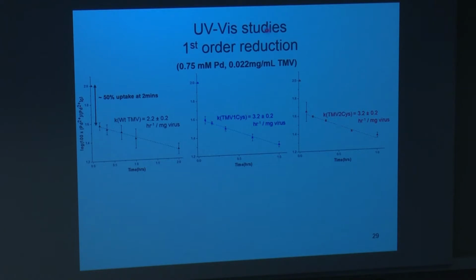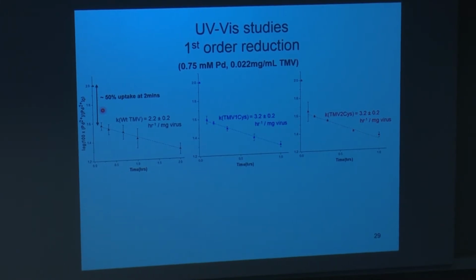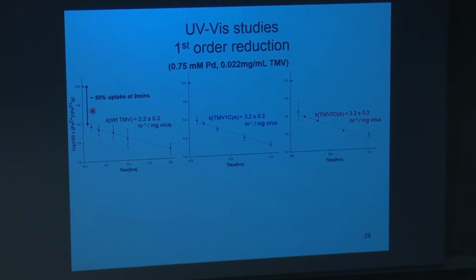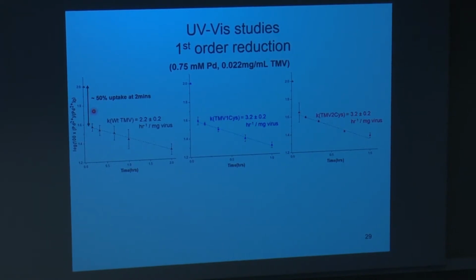And using the UV-Vis spectrophotometer, we had an initial solution of 0.75 millimolar palladium and 0.022 milligrams per milliliter of TMV. The initial solution was here at level 2, and this axis here is log of 100 times the palladium ion concentration at time t divided by the initial palladium concentration. You see this big drop in the first couple of minutes of the reaction, but afterwards there was this kind of first order reaction kinetics exhibited by the reduction of the palladium.